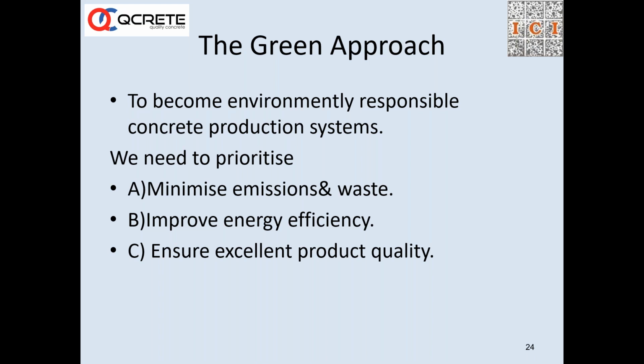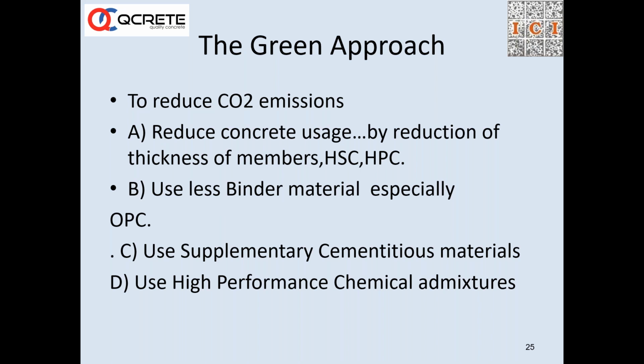So what is the green approach? The green approach is to become environmentally responsible and make better concrete production systems, minimize emissions and waste, improve energy efficiency, ensure excellent product quality. So by having complete control on the mix design and water cement ratio and usage of good materials, including SCMs, we can ensure better quality, and we can reduce the emissions also. So reduce the concrete usage by reduction of thickness of members, use less binder material, especially OPC, as we have discussed, use supplementary cementitious materials, use high performance chemical admixtures.